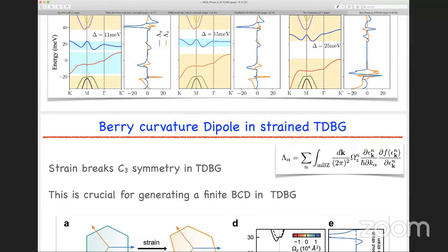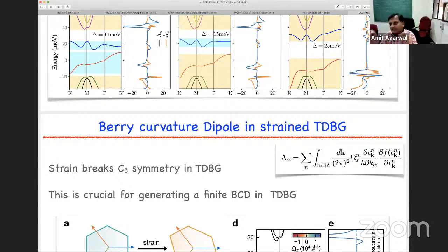So the simple thing is, all of these signals are very difficult to separate. What I do is I apply a current and measure a voltage. To know whether this voltage is coming from first order, second order, or third order is very, very difficult. Experimentally, one way to do it is to apply an incoming current with a frequency omega, so let's say I goes as I0 times e to the power i omega t, the real part of this. Then I squared will go as cos 2 omega t, and you can do lock-in measurements where you separately measure just the 2 omega signal. Experimentally, it's easier to measure.